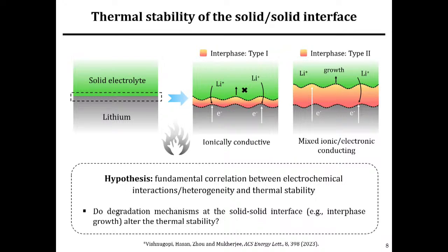However, in our recent work, which just got published, we showed that non-flammability does not necessarily translate to thermal stability. The main reason is that solid electrolytes are chemically unstable with lithium, and they can potentially have resistive interfaces, and these interfaces can be of various types—they can be kinetically self-limiting, or they can also be progressive in nature.